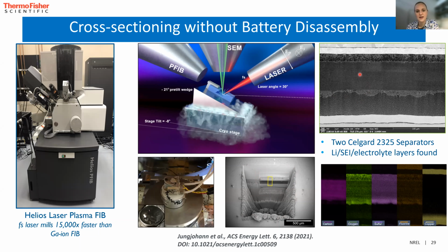Then, using imaging in the SEM and EDS mapping, we were able to identify the different layers of the battery stack. You have the copper, then electrodeposited lithium, which is very dark, intermixed with some electrolyte and SEI. Then we had two Celgard 2325 separators, which were polyethylene and polypropylene, where we could see the different polymer layers in that separator. Below that we had electrolyte filling in toward the lithium metal counter electrode, which was that large deposit, with a copper electrode below.